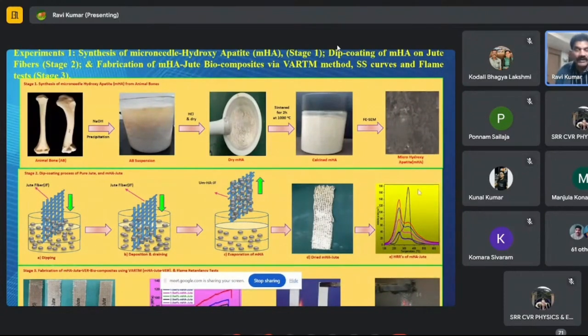So later we go into the dip coating on the fabric. We took different weight percentages of the MHA in ethanol or any suitable solvent, and we put it under stirring.